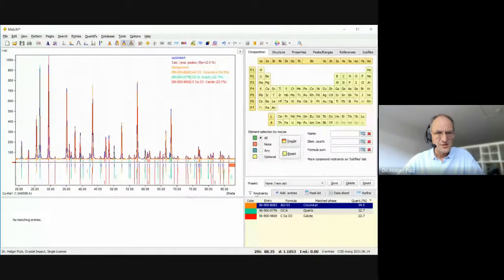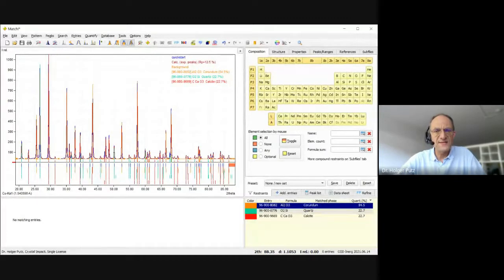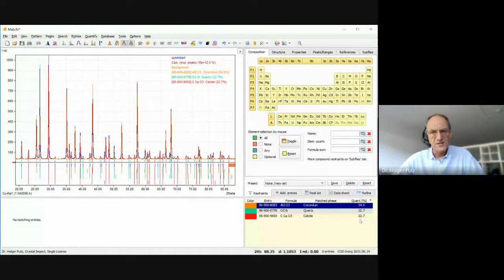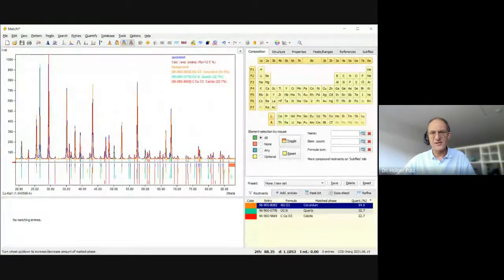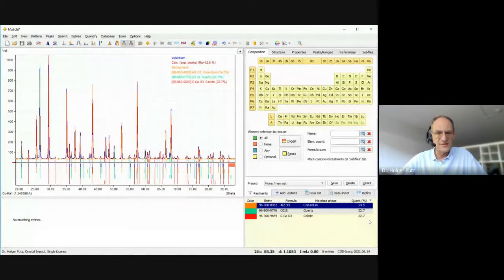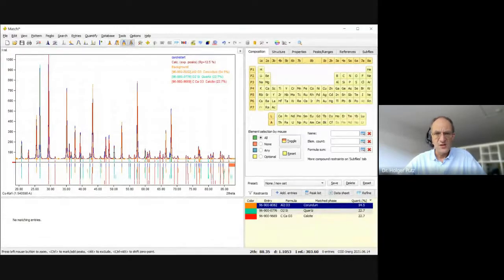So, okay. Now, as you can see in the match list also, along with the selection of the phases, Match has already performed a quick quantitative analysis. That is, it has used the so-called reference intensity ratio method, which is based on the peak scaling factors, to give an arbitrary first quantitative analysis, as you can see here. We would like to improve these values now by running a short Rietveld refinement in order to give some better results. And in order to set up a Rietveld refinement calculation for these three phases and the experimental diffraction pattern,